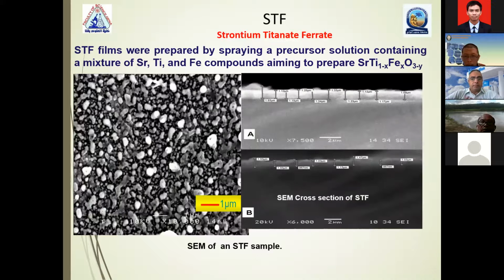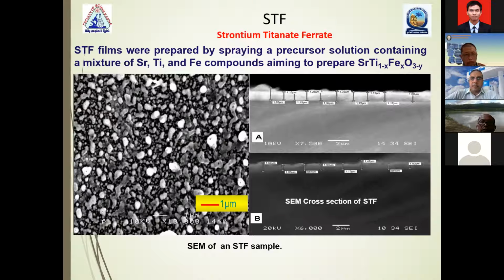Another family of materials to be used for water splitting, or as an electrode for solar cells, is strontium titanate ferrate. It was made actually accidentally, by mixing strontium, titanium, and iron salts, then spraying on a hot substrate, and by annealing it comes out as this material, which was maybe the first perovskite I prepared, even before the discovery of perovskite, like 2008.